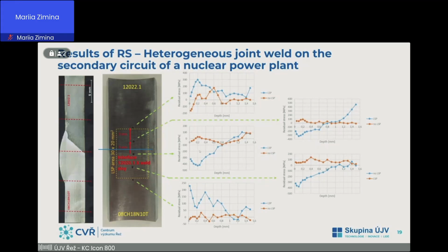And the most important chart is in the center. As you can see, the orange curve is before LSP, base material, and the blue curve is after LSP. And as you can see, the compressive residual stress increased from 0 to 50 megapascals up to 450 megapascals. And the compressive residual stress was measured up to 1 millimeter.